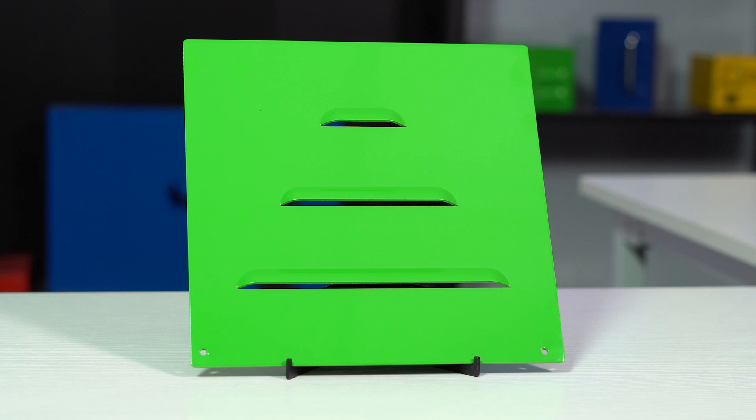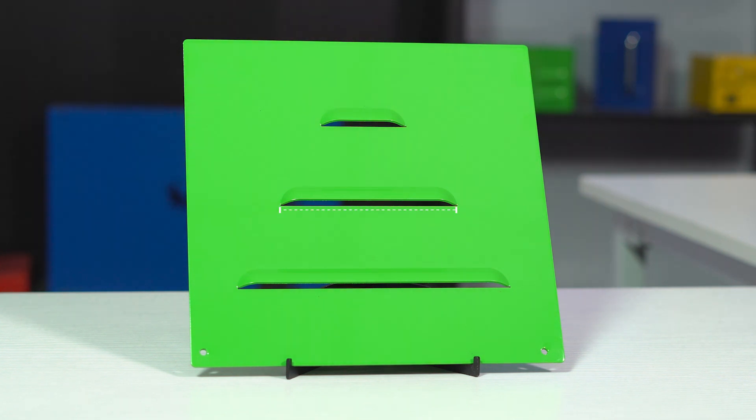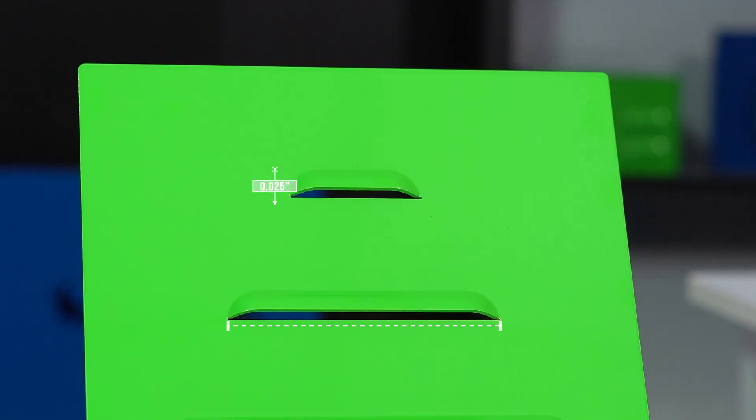So let's talk constraints and requirements. Before a louver can be created with a press brake, the material will be cut with a pre-slit that will be 0.1 inches wider than the louver size of 2 inches, 4 inches, or 6 inches. The opening will always measure 0.025 inches high.